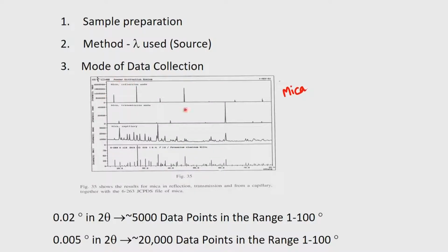This is the pattern you will get. So, you are going to get effectively 1, 2, 3, 4, 5, 6, 7 peaks. The XRD is of course 0 to 80 degrees, which is shown here. So, you will get peaks corresponding to these HKL positions. You can find out the HKL positions because from 2 theta you get the d values. From d you can find out what those HKL values are, once you know the a, b, c, alpha, beta, gamma. You know that methodology.